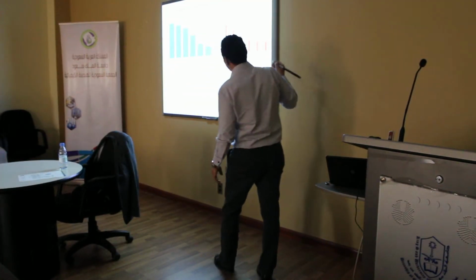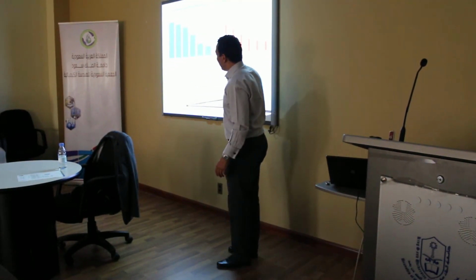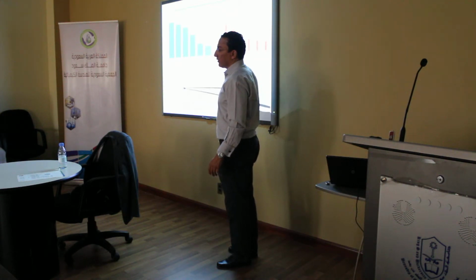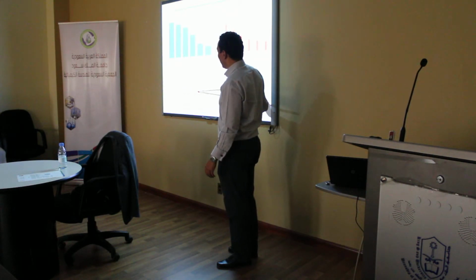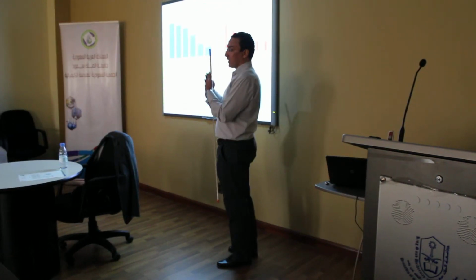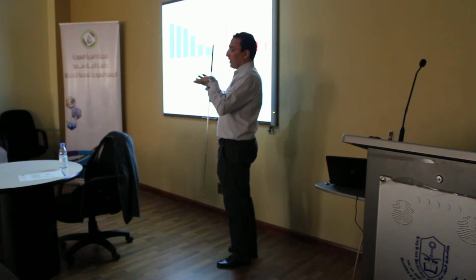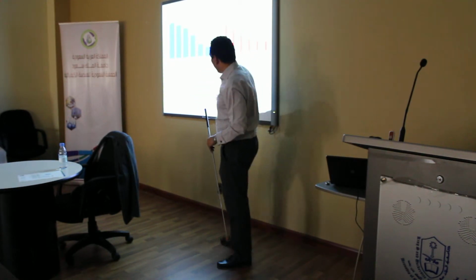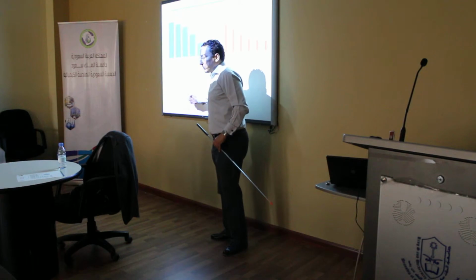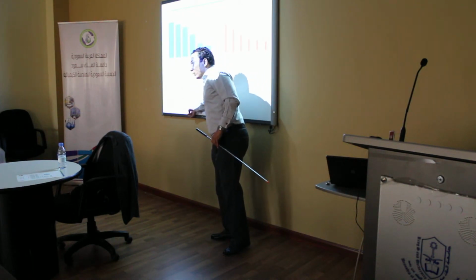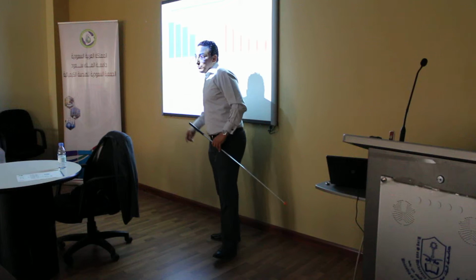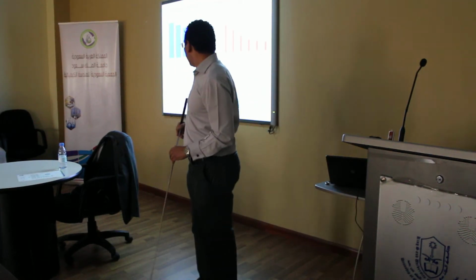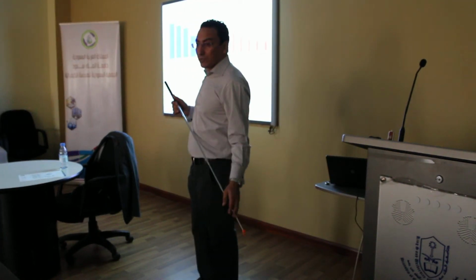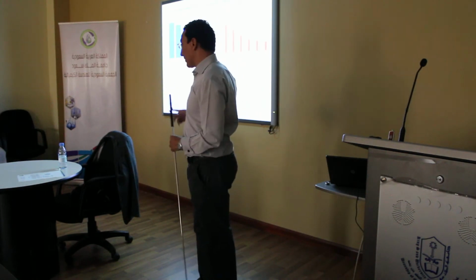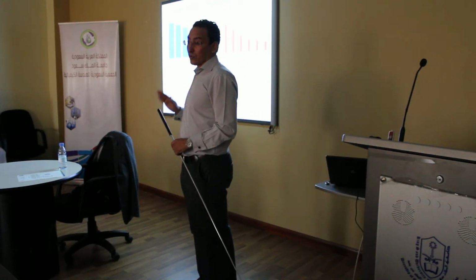The other membranes, you can see here that we can get very high separation factor. It's 99.995, all of them. So it's very integrated, and the fibers are very fused together, leading to the concentration of the permeate being lower, down to 3.6 microsiemens per centimeter, which is very good. And we used this type of membrane for 5 hours or more.